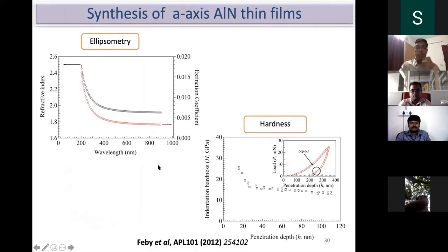We have studied ellipsometry to find out the refractive index. With different wavelengths, the refractive index can be tested, as well as the extinction coefficient, which decreases with the wavelength of the light. Around 546 nanometer wavelength light, we got 1.93 as the refractive index of the material, roughly. So this is the visible range I am talking about.